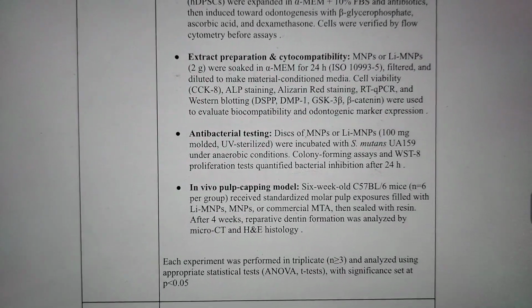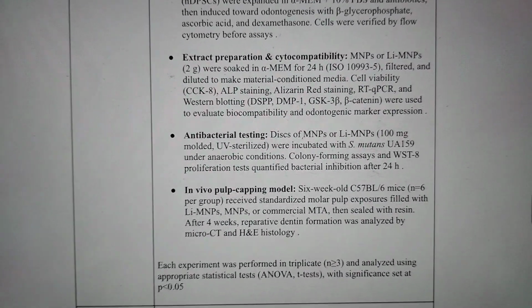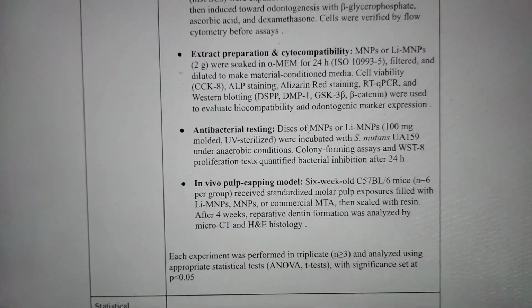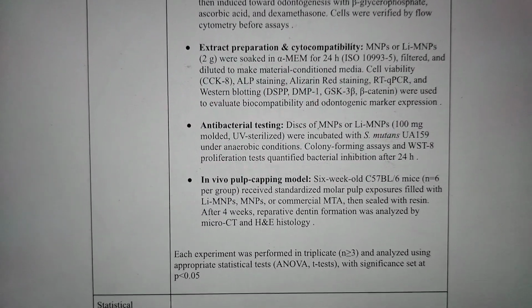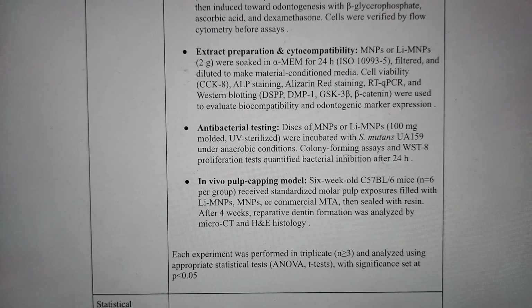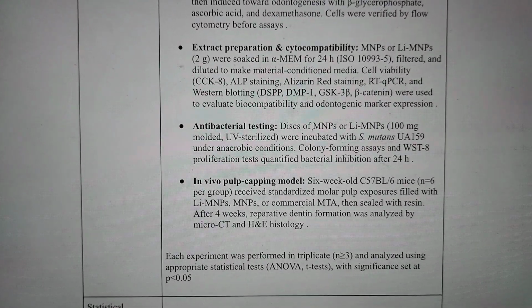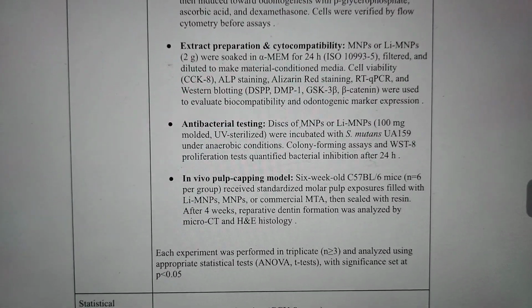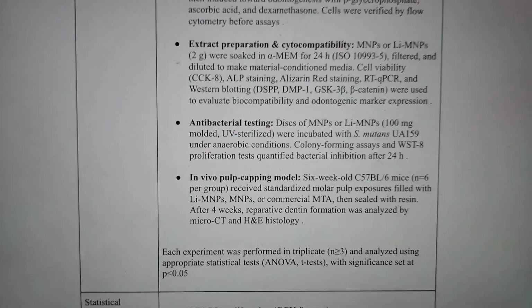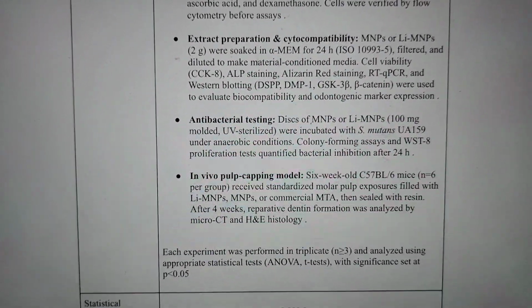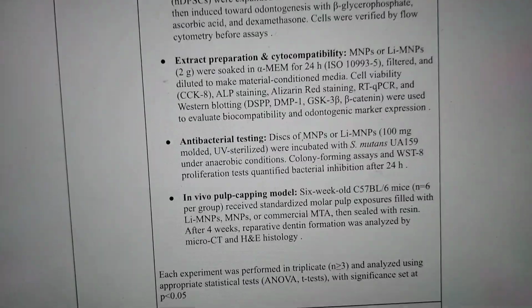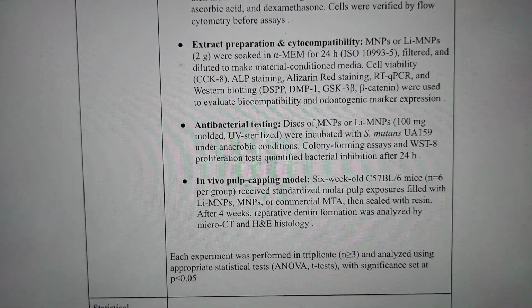Antibacterial testing was done. Discs of the developed nanoparticles were incubated with S. mutans UA159 strain under anaerobic conditions, and colony forming assays and WST-8 proliferation tests were done to quantify bacterial inhibition after 24 hours. In vivo pulp capping.